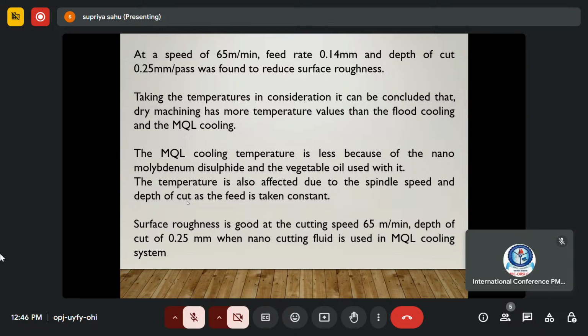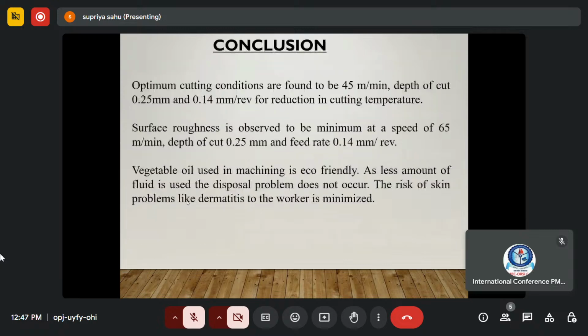Taking the temperature into consideration, it can be concluded that dry machining has a higher temperature value than flood cooling and MQL cooling. Then the MQL cooling temperature is lower because of the nano molybdenum disulfide and the vegetable oil used with it. The temperature is also affected by the spindle speed and the depth of cut, as the feed is taken constant. So here the surface roughness is good at the cutting speed of 65 meters per minute and depth of cut 0.25 mm when the nano cutting fluid is used in the MQL cooling system.